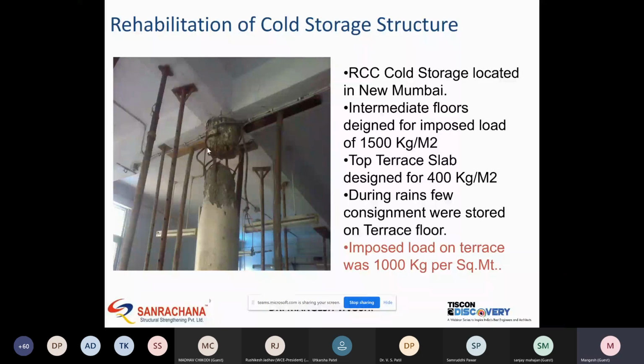RCC cold storage structure located in Navi Mumbai. Intermediate floors were designed for higher load because it was mainly used as a storage building, 1500 kg per square meter. But the top terrace was designed only for 400 kg per square meter. And what happened during the rain? Whatever material was lying in the compound was kept on the terrace and covered with tarpaulin. But in the process, they missed the fact that they had loaded almost 1000 kg per square meter, and this frame, this floor, was not designed for that type of load. So you can see these beams are cracking, these columns are failing, and because of this overloading, this failure happened.